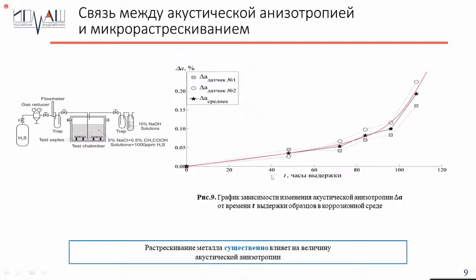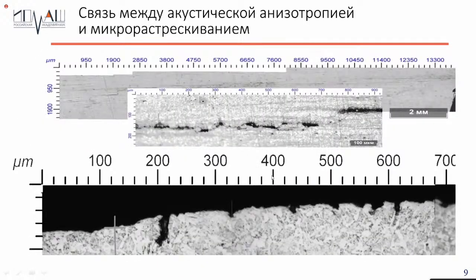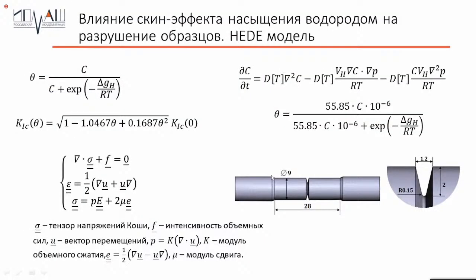And so the surface layer, which defines plastic waves, is closely related with hydrogen reaction in the thin surface layer. And you can see the surface effect, which influences the flatness of deformation. In this surface layer, you can see the crack formation, as well as black holes formation, pores formation.